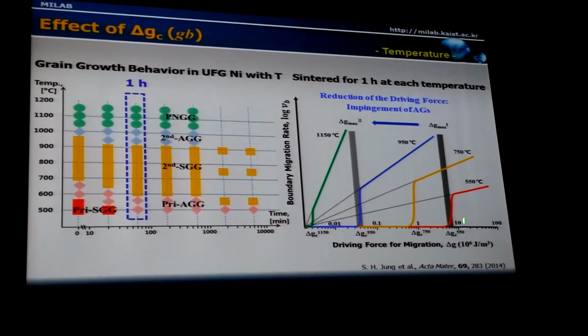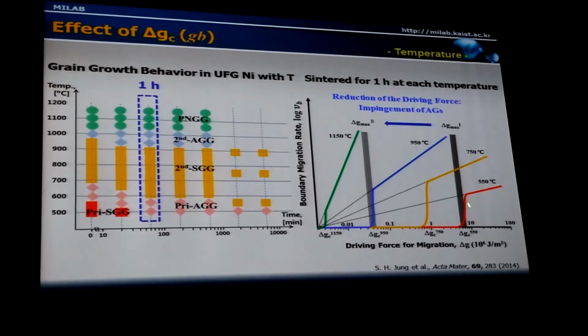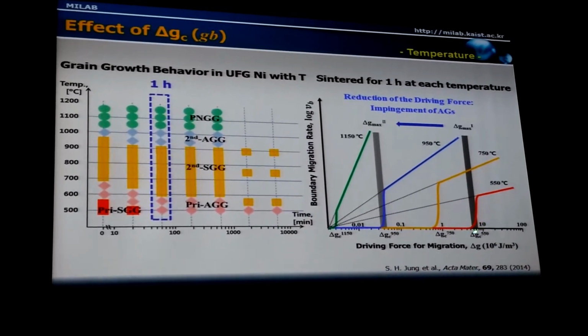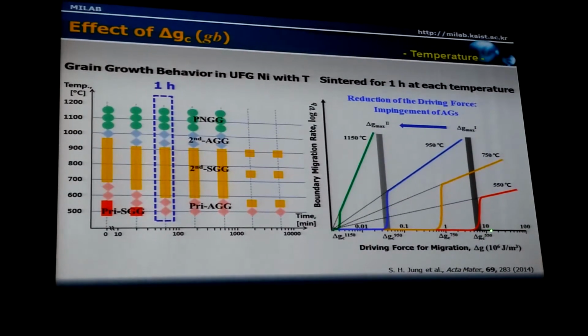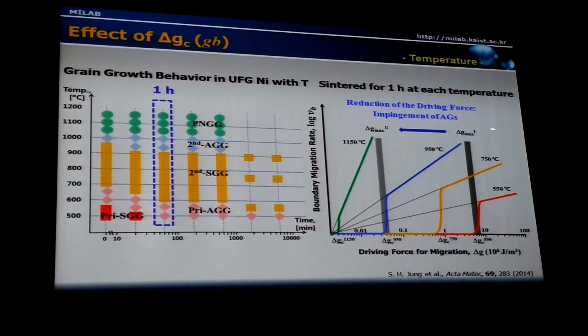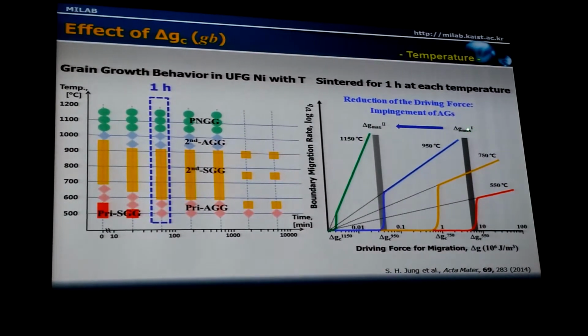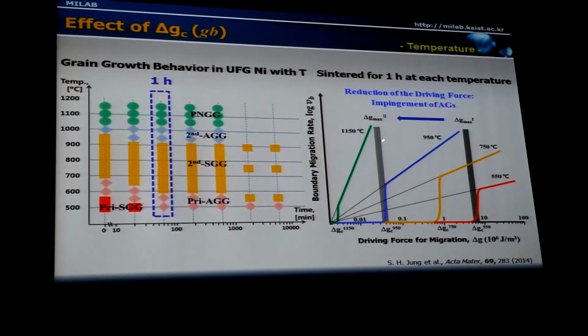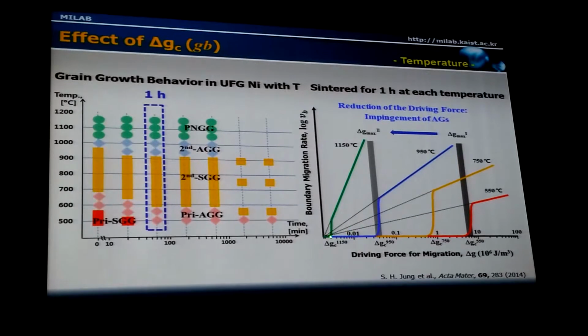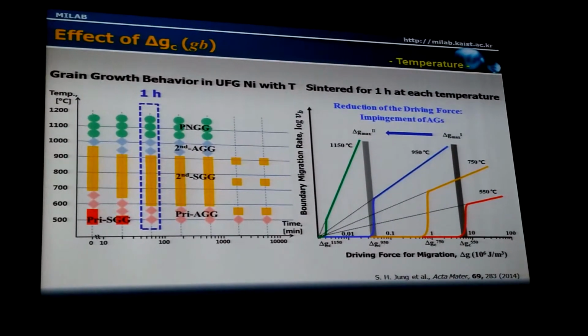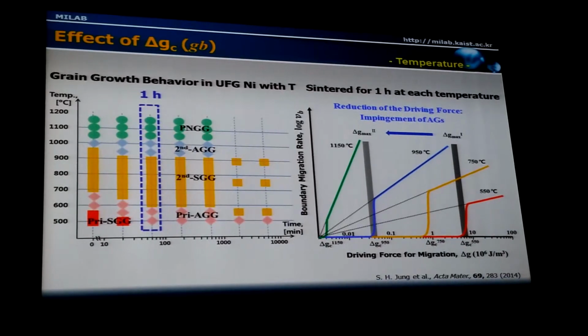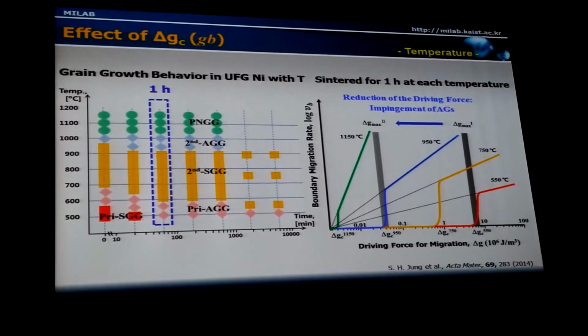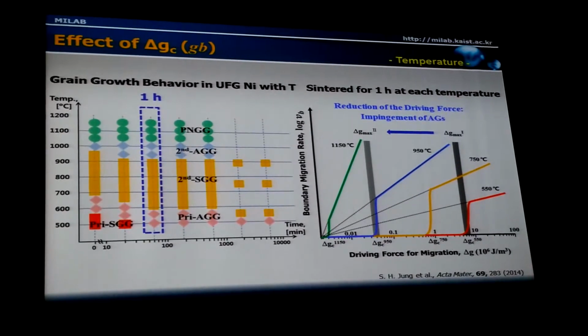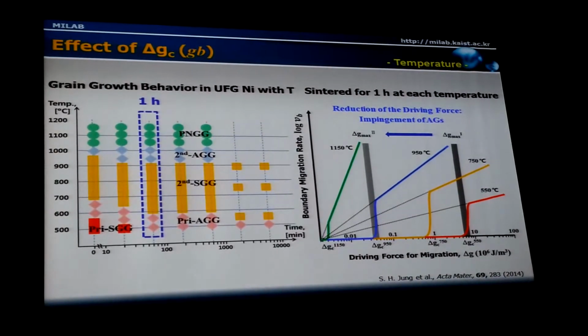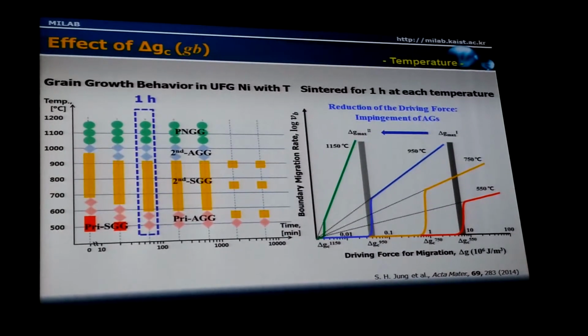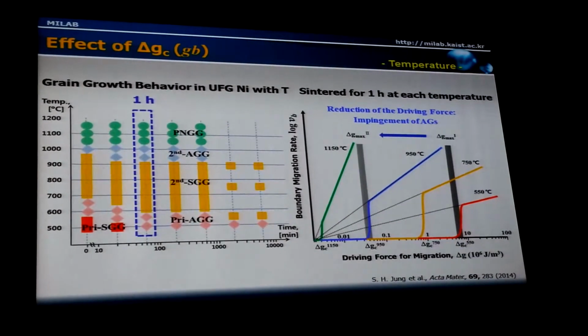So at low temperature, 550, the maximum driving force is comparable with the critical driving force. Then some of the grains grow abnormally. But after the abnormal grains impinge upon each other, the maximum driving force of course decreases considerably. And at high temperature, normal grain growth occurs. So all these experimental observations are in accord with the prediction based on the nonlinear migration behavior of the boundary and the mixed control model of grain growth.